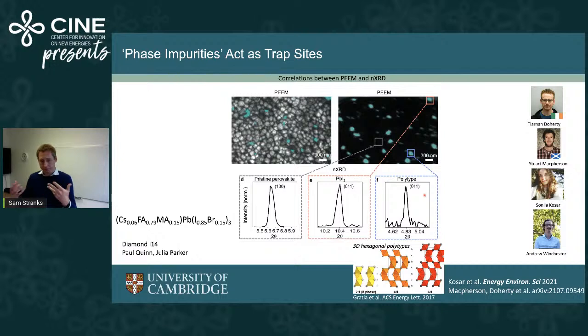And so these are different structural forms. There are many, many different types of hexagonal polytype for these halide perovskite units. The most famous, or most well known, is the delta phase of these formamidinium-rich samples, the 2H polytype. There are also these various linear combinations of these structures as well, where you get the 4H and 6H as well, and there are others as well. But we can see that these polytypes do correspond to deep trap states as well. So these small impurity phases in the film are problematic.